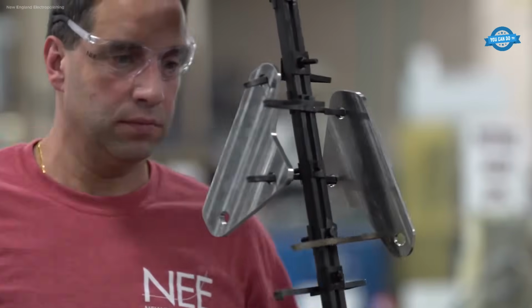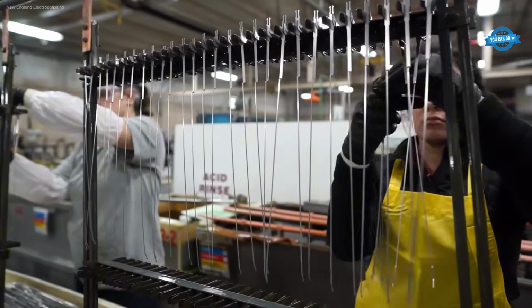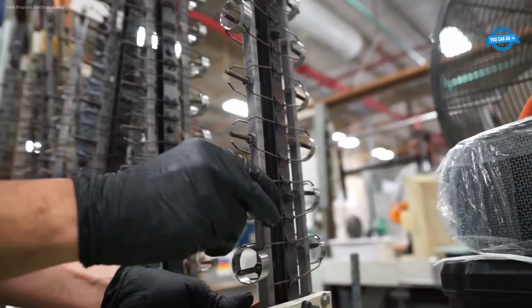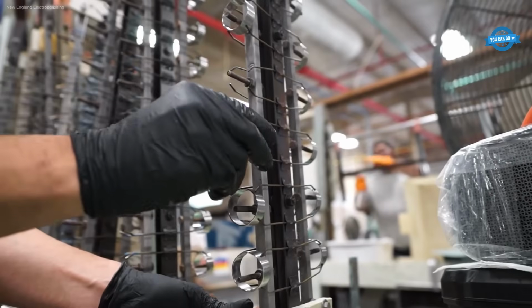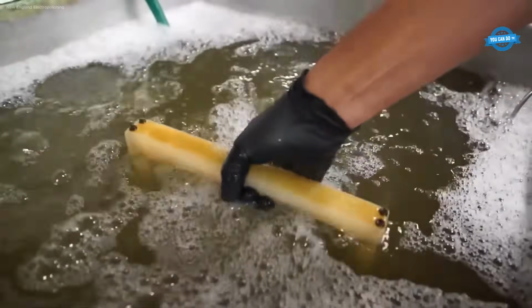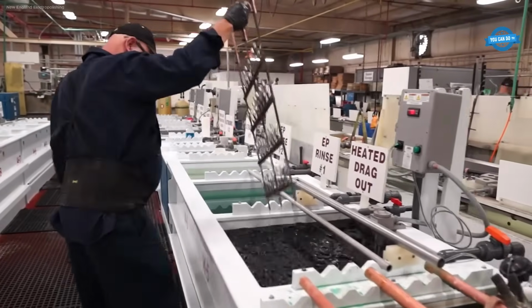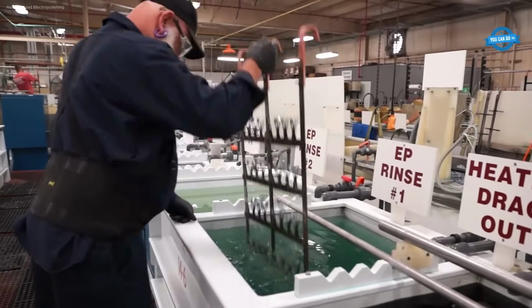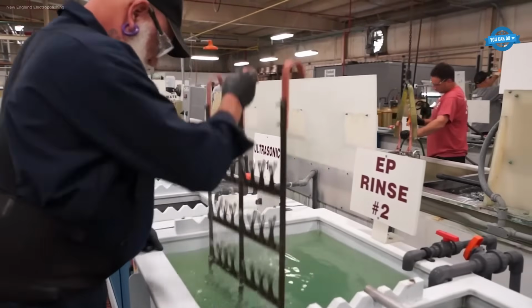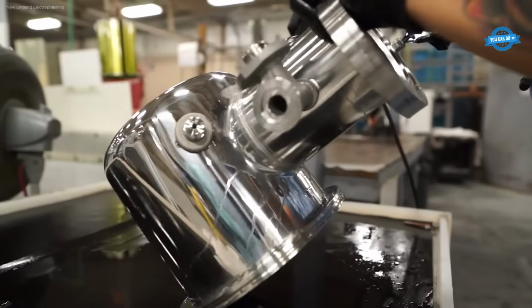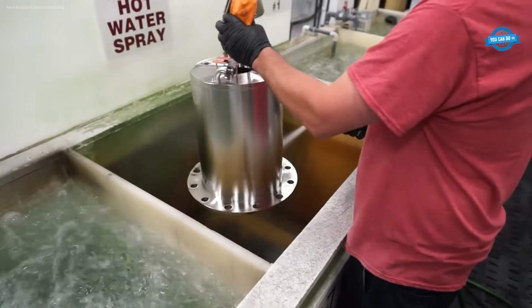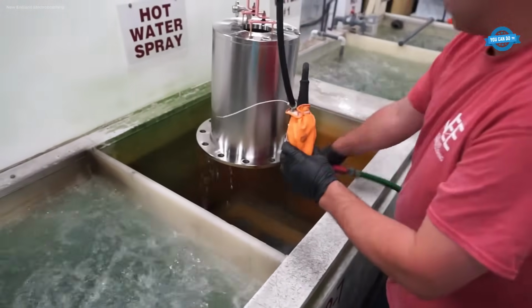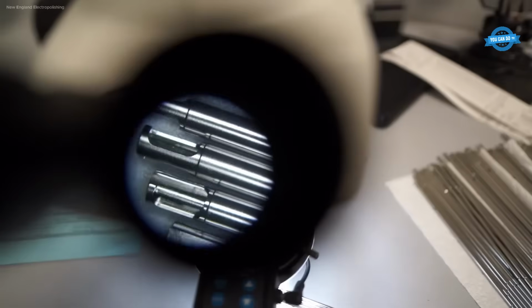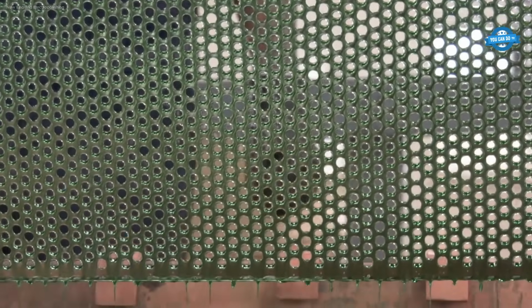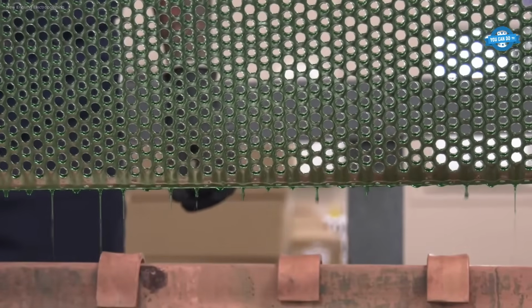Electropolishing is a highly controlled electrochemical process used to enhance the surface of stainless steel components. Unlike mechanical polishing, it removes microscopic peaks and embedded contaminants by dissolving a thin layer of metal. By applying DC current in a temperature-regulated acid bath, usually a mixture of sulfuric and phosphoric acids, the process levels the surface at a microstructural level. It not only creates a bright, reflective finish, but also improves corrosion resistance by removing free iron and exposing a richer chromium oxide layer.